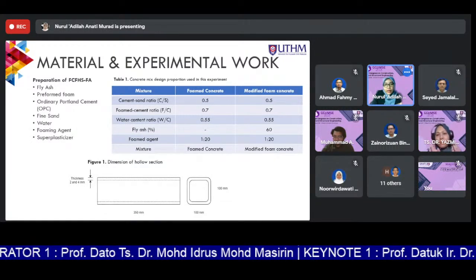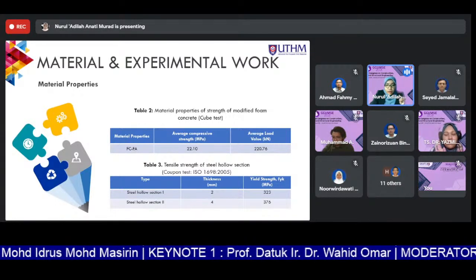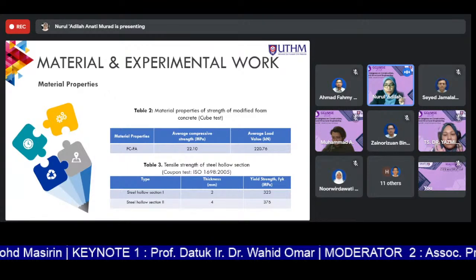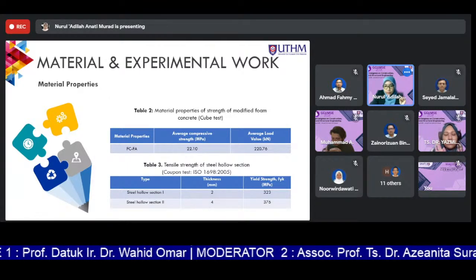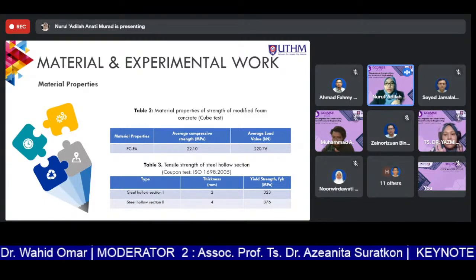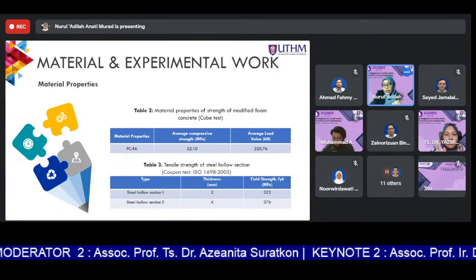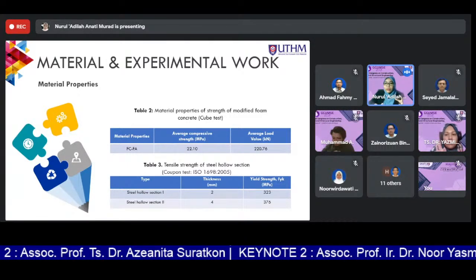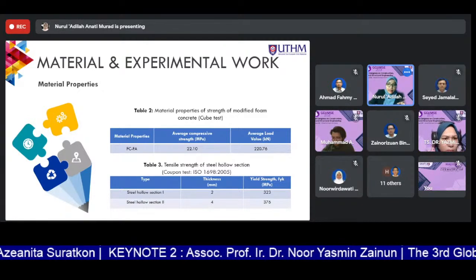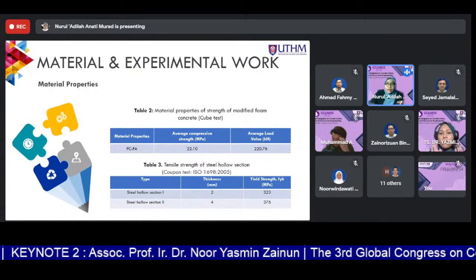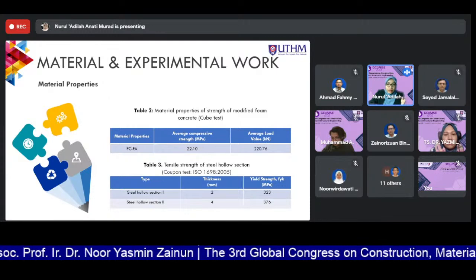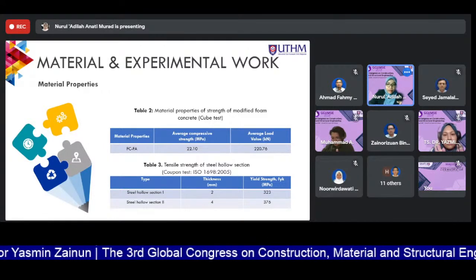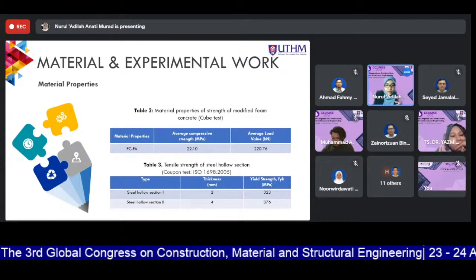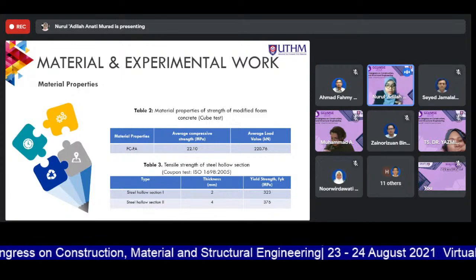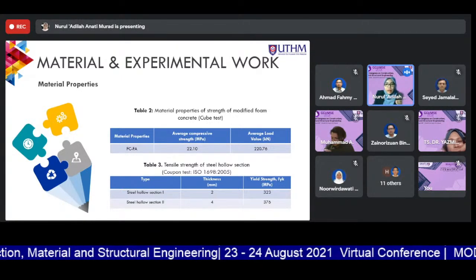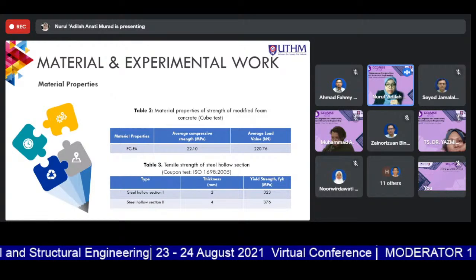And for the material properties, okay, the strength of the modified foam concrete after the cube test is 22.1 megapascal, and the cube test for the modified foam concrete has an average load value of 220.7 kilonewton. And this cube test was carried out to determine the strength of modified foam concrete at 28 days. And the tensile coupon test was carried out to determine the strength of the steel hollow section according to ISO 6892-1:2005. And this Table 3 shows the tensile strength for the thickness 2 millimeter is 323 megapascal, while 4 millimeter is 376.